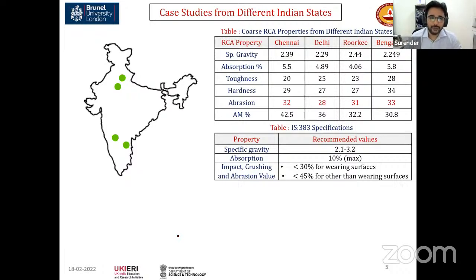So what we did, we went to different recycling plants. We collected the data to see what the range is. Is there any difference in the quality of the recycled concrete aggregate? We did it in Chennai for multiple plants, but here I'm showing only the average values for Delhi, Roorkee, and Bangalore. What we found is that the specific gravity is more or less the same. Water absorption, this is only the coarse fraction. For the finer fraction, the specific gravity was around 2.1, and the absorption for the coarse fraction was near 5 to 6%, and for the fine aggregate it was 8 to 12%. That means it is significantly higher.